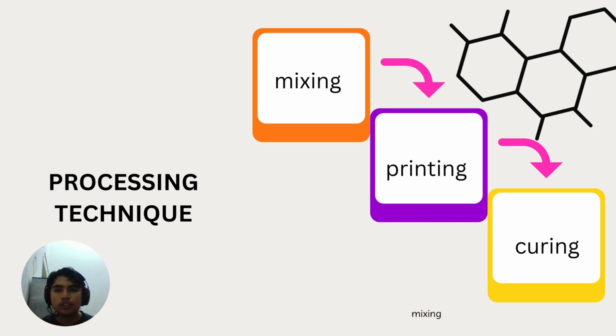The mixing process is used to combine the PEDOT, graphene, and polyethylene terephthalate (PET) in the correct percentage based on the best formulation. The operation then proceeds with a mixing process that takes around 10 minutes at room temperature. A well-dissolved mixture was created by using a proper stirring technique, stirring in one direction at a steady speed.